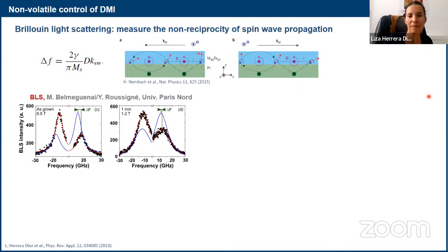This could be probed with Brillouin light scattering by measuring the non-reciprocity of the spin wave propagation. I will not go too much into detail, but in principle, because of this chirality, we could see a shift in the frequency of the spin waves, let's say, winding in opposite directions.